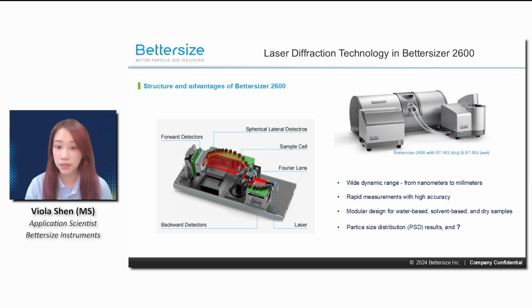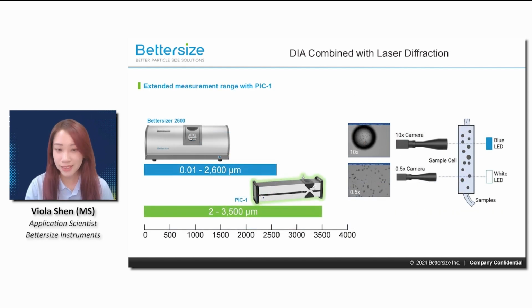Moreover, the latest module of the Bettersizer 2600 has recently debuted, offering enhanced capabilities that extend beyond just particle size distribution results. Yes, that is particle shape analysis. Owing to its modular design, the Bettersizer 2600 effortlessly integrates a dynamic image analysis system, PIC1, which extends the measurement range up to 3,500 microns and provides quantitative particle shape analysis in real time. From the figure on the right side, we can see that the PIC1 features a dual camera dynamic image system. As the dispersion system transports particles through the sample cell, the high-speed camera captures and converts images to digital format for real-time analysis. Enhanced with PIC1, the Bettersizer 2600 can now provide particle size distribution and shape analysis simultaneously.